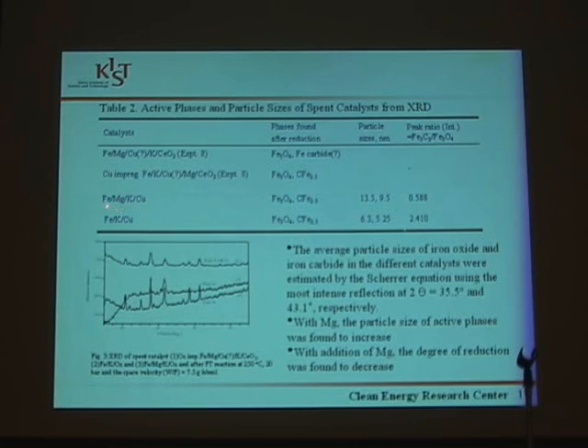Then this is a promoted iron catalyst. It has shown Fe3O4 and carbon Fe2.5 as active phases with the particle sizes 13.5 and 9.5, and the peak ratio of these two was 0.588, and for only a precipitated iron catalyst, it was 6.3 to 5.25, and the ratio was 2.4. So this is an XRD pattern of the spent catalyst for the first sample, copper, magnesium, and ceria. Then this is the precipitated iron catalyst, and this is the magnesium promoted iron catalyst.